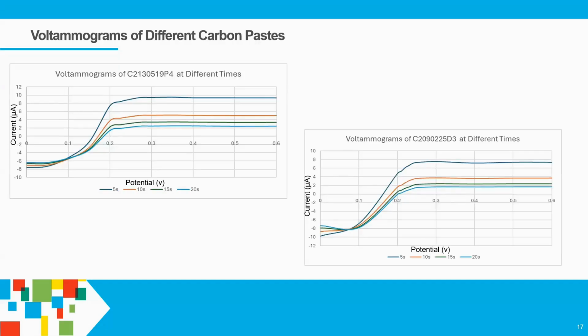So here we have the P4, which was in our earlier example with the cyclic voltammogram, and we have the D3. Straight away you can see at 5 seconds, there's a difference. This is something that the cyclic voltammogram didn't tell us. So this is how we want to represent our data, via voltammograms, showing which one's best for what type of mediator. We chose a selection of times, 5, 10, 15, and 20, because different reactions will take different times.